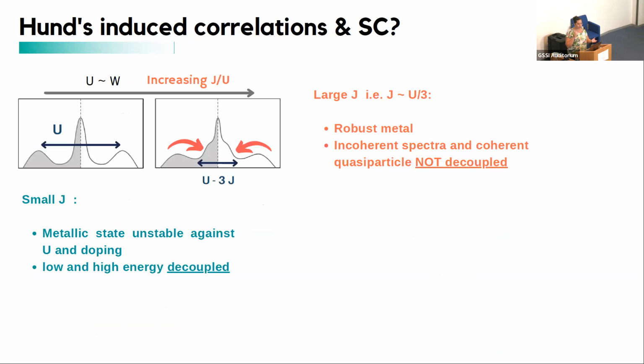So I would say that the main difference between a low Hund's value and a large Hund's coupling value, close to, for example, this 1/3 value, is that you have a very robust metal in the Hund's metal, and the incoherent spectra and the coherent quasi-particles live very, very close, in a very narrow energy range. So they are not completely decoupled.